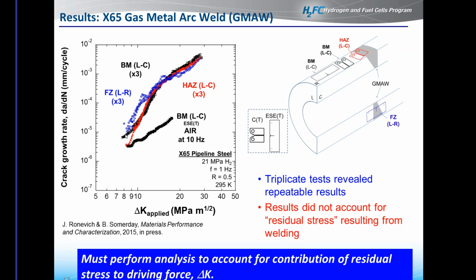One thing we did notice is, one, we do know that this pipe does possess residual stress. Now, residual stresses are innate due to the welding process, and actually there was some other research done on this pipe that did show some significant residual stresses. And so what we're really interested in is understanding what the effects of the microstructure are to the unknown driving force. And really the residual stress is kind of masked a little bit in what our driving force is in this case. So we knew we needed to perform a little bit more analysis to tease out what was going on with residual stress and how it was influencing our applied driving force, or the effective driving force, I guess.